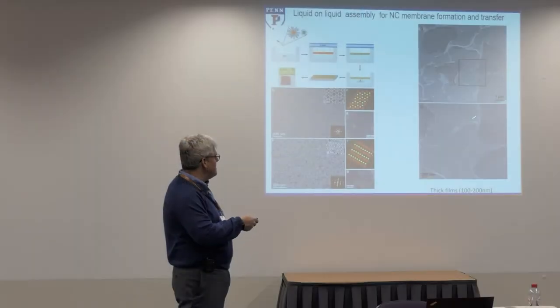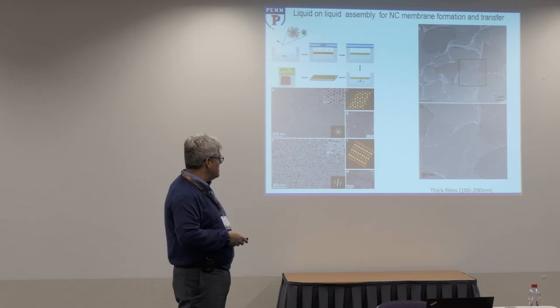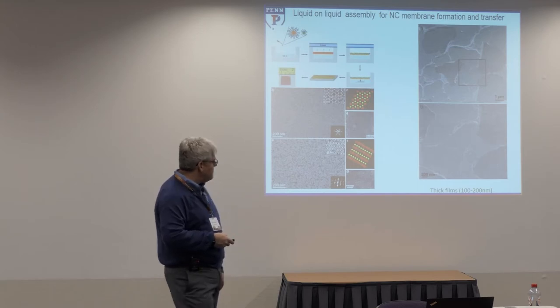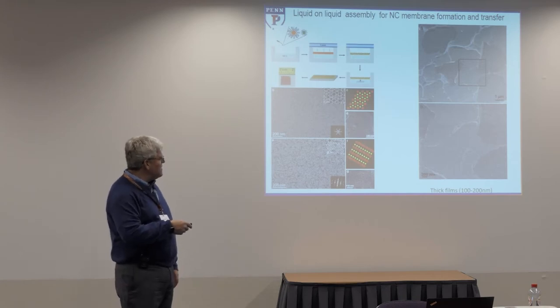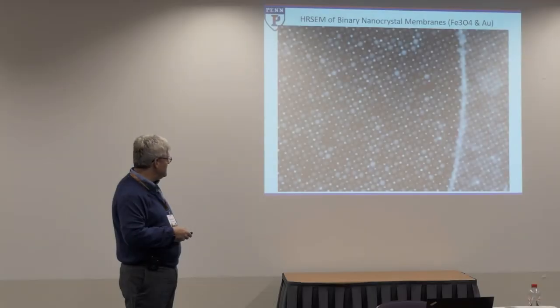And that is a limitation for certain applications where transport across grain boundaries is potentially problematic for devices. But actually, for many of the devices that we make, the active area of the devices is much smaller than the size of the grain boundaries or defects. So the one thing that we need to understand is, how do we control it so that we minimize the probability that if it has a defect, it'll end up in a part of the device that matters? That's still a bit of a challenge in this piece.